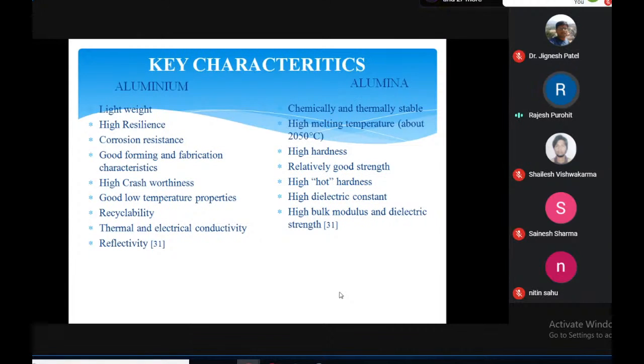And then aluminum oxide, which is also called alumina, also has very good properties: it is chemically and thermally stable, with a high melting temperature of about 2050 degrees centigrade, high hardness, relatively good strength, high hot hardness, that is hardness at high temperature, then high dielectric constant, and high bulk modulus and dielectric strength. Because of these good properties, if we reinforce alumina in the aluminum melt, we get better mechanical and various physical properties.